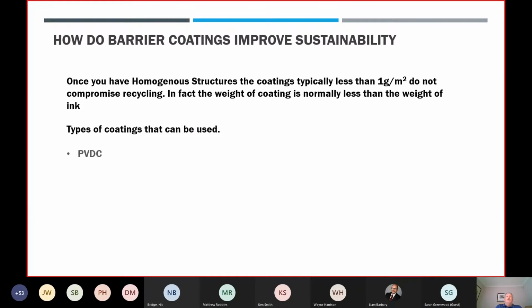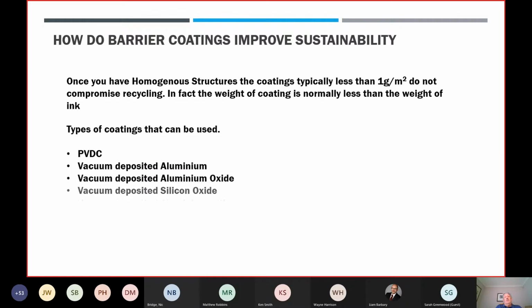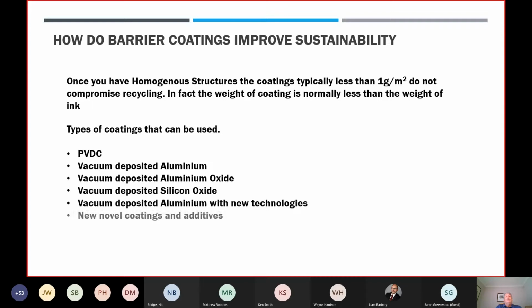How do barrier coatings improve sustainability? Once you have homogeneous structures, the coating is typically less than 1 gram per meter square. As I've said, don't compromise recycling. And quite often, the weight of the coating is less than that of the ink.